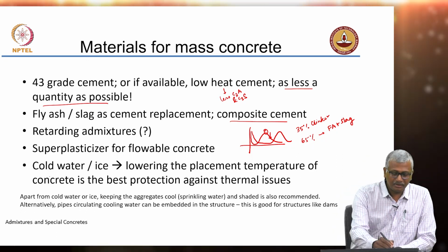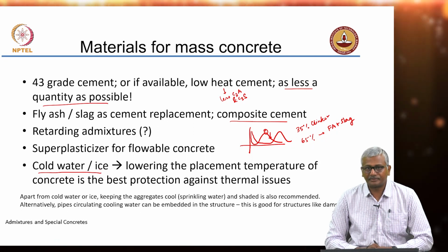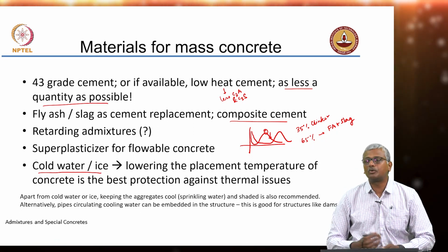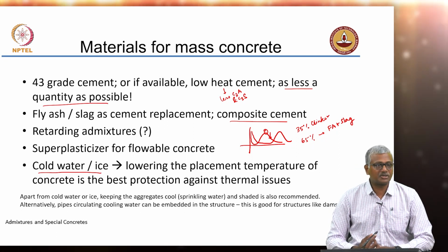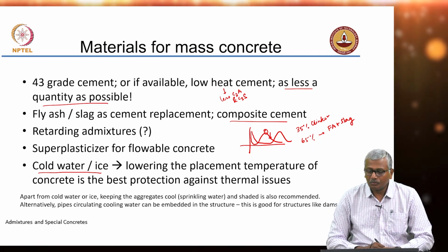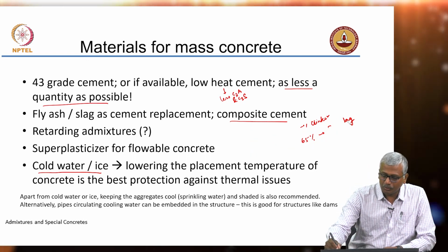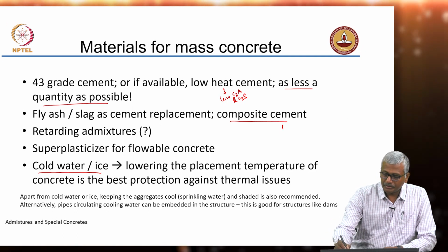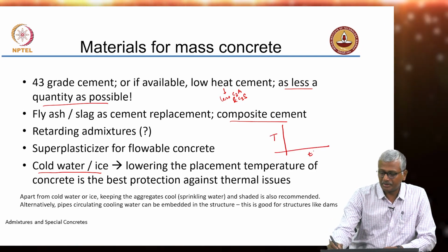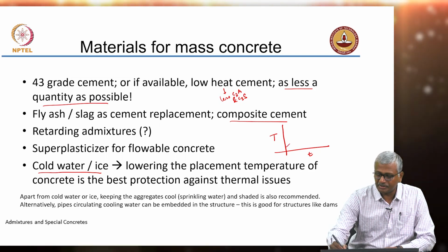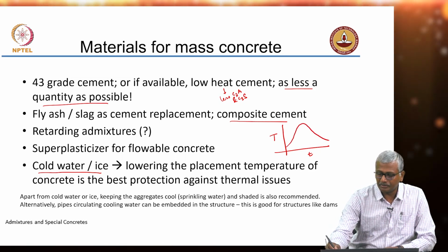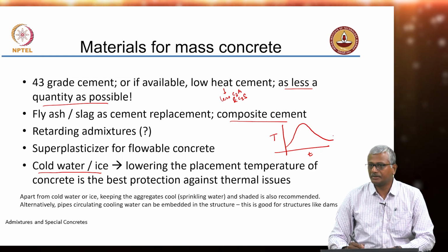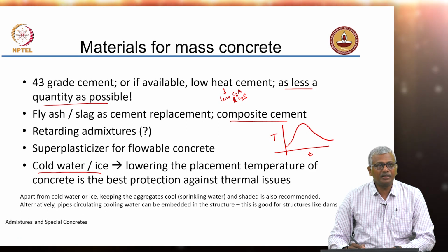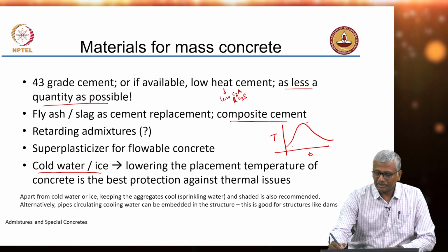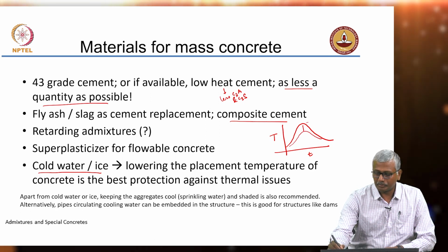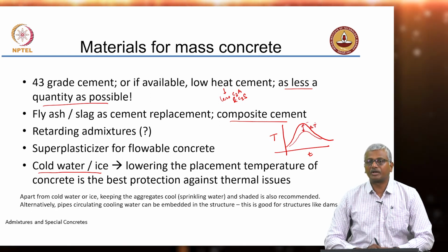Then the main ingredient, cold water or ice. We will talk about this in more detail later. Ice is obviously more desirable than cold water because it has the potential of reducing temperature significantly. So, what you are trying to do here by using cold water or ice, so let us say this is my temperature versus time graph. I start off at the temperature of placement, temperature of concrete goes up and then reduces to ambient conditions, right. The problem comes when different segments of the concrete are exposed to different temperatures. This delta T is what we worry about, right.